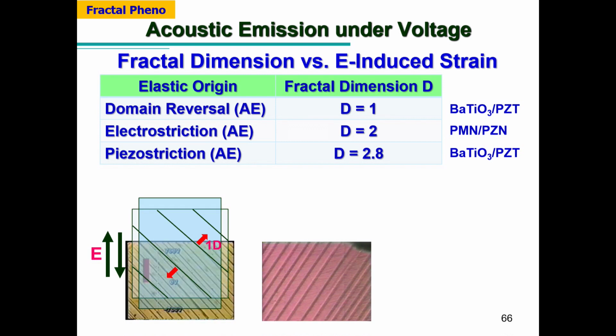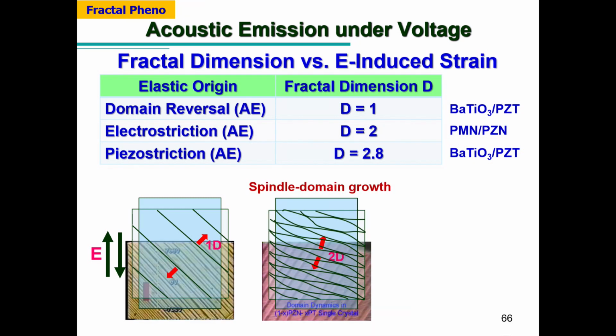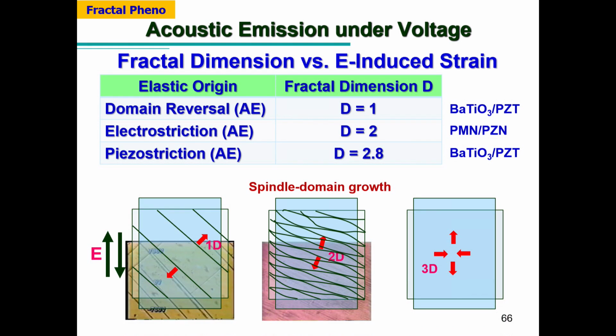And electrostriction, to the contrary, as you remember, has spindle-like domains, fat or slim, so two-dimensionally moving. Therefore, for electrostriction we can expect fractal dimension 2. Piezostriction is already saturated. Therefore, the extension and shrinkage are all three-dimensionally moving, so the fractal dimension is expected close to 3. Okay? This is a visualization of fractal dimension. So if you measure the fractal dimension, we can speculate the domain motions.